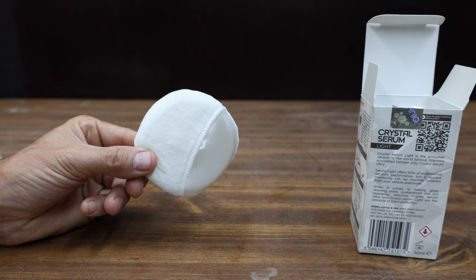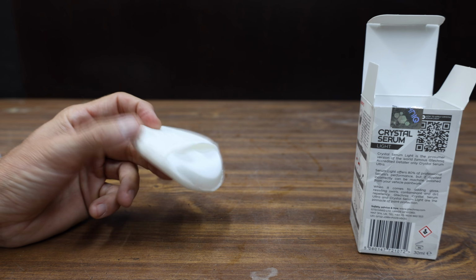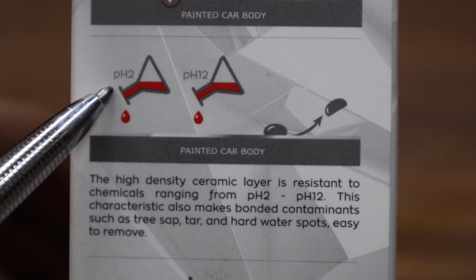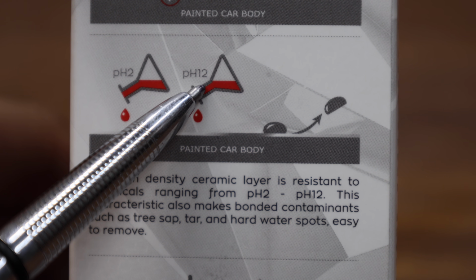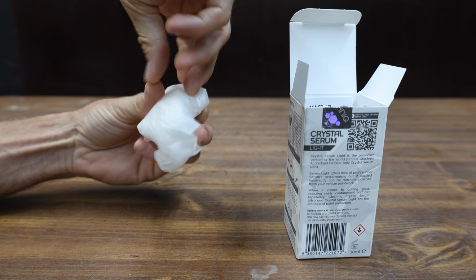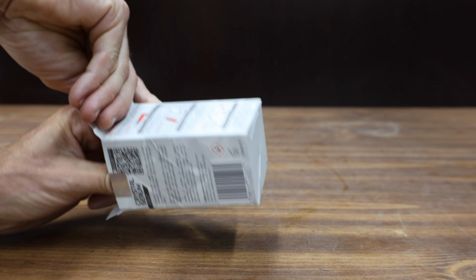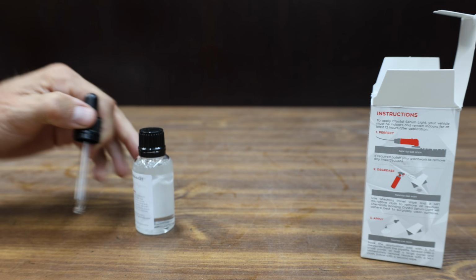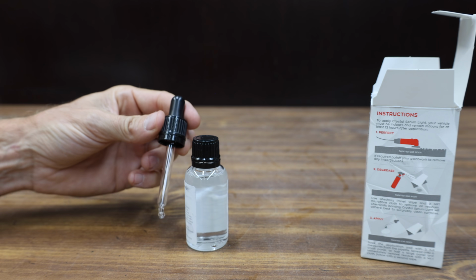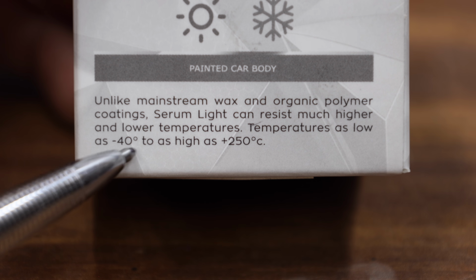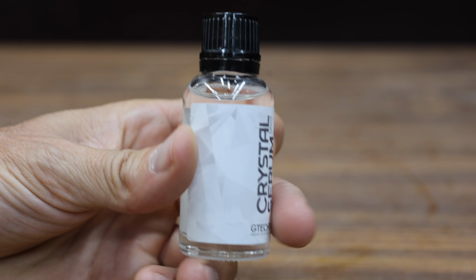The previous products are spray-on products, but this one requires an applicator. They claim their high-density ceramic layer is resistant to chemicals ranging from a pH 2 to a pH 12. The Gtechniq is made in the United Kingdom. Unlike mainstream wax and organic polymer coatings, Ceramlite is supposed to resist much higher and much lower temperatures, as low as -40 degrees Celsius and as high as 250 plus.